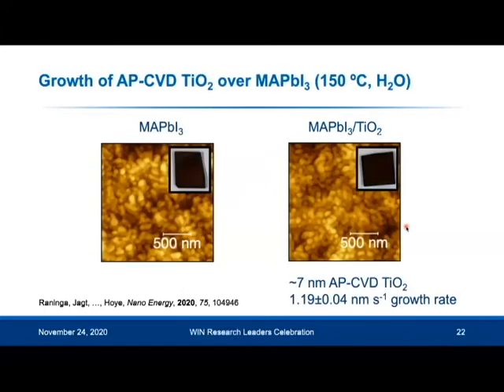So first of all, this is what happens when we grow APCVD TiO2 over methylammonium lead iodide. And we're taking the worst case scenario. We're using the strong deposition conditions with the most thermally sensitive perovskite. And you can see that it stays the same. And this contrasts to what I showed you earlier, where people use ALD to grow TiO2 at only 100 degrees Celsius. And after the 1 hour it took to grow 10 nanometers, the perovskite completely degraded.